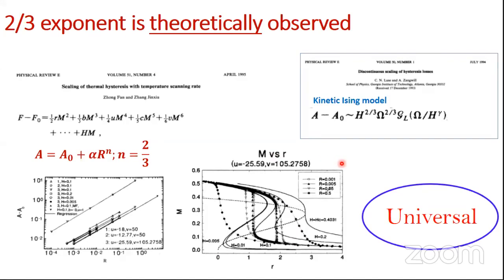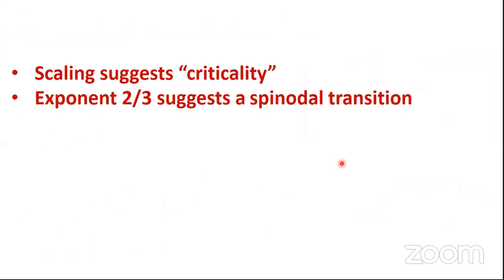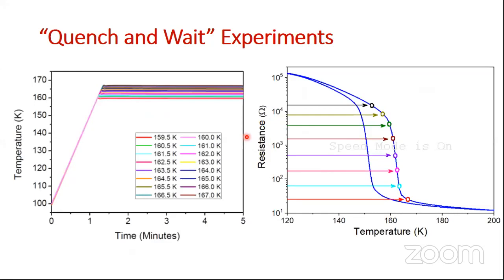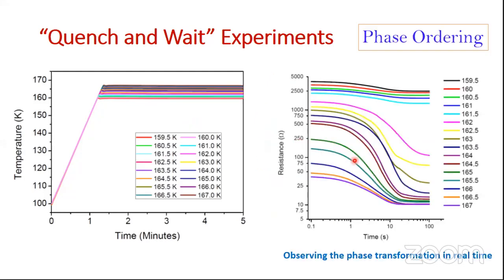So now I will shortly summarize the talk: the scaling suggests some kind of criticality, and 2/3 suggests the spinodal transition. Now I will come to the next experiment, which is called critical slowing down. The experimental technique is that we start from very low temperature, quickly quench to this transition region, and wait for some time. And this is the temperature profile of this measurement. Now we are looking at the resistance evolution with time, and this is also called the phase ordering measurement.